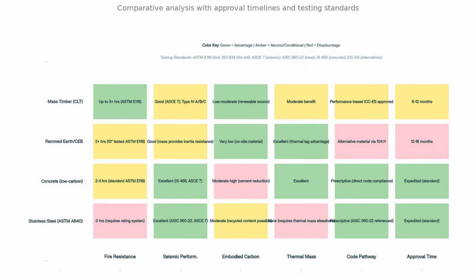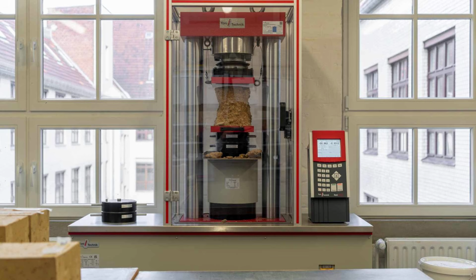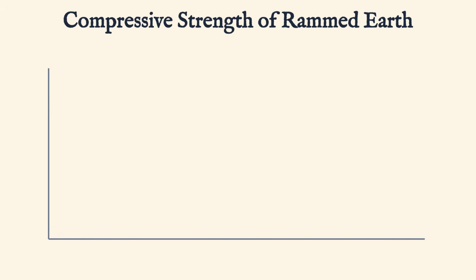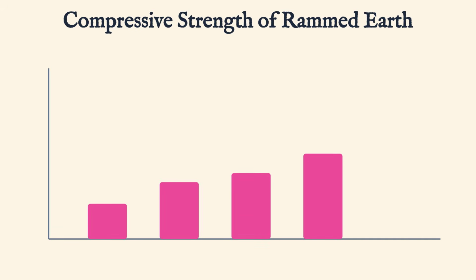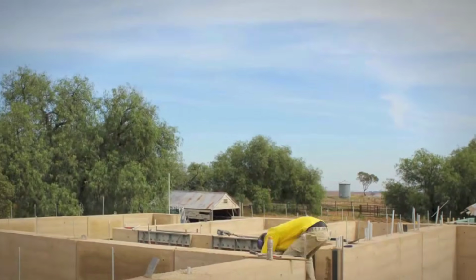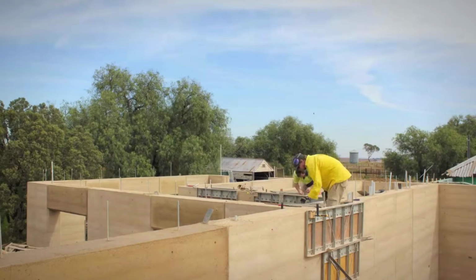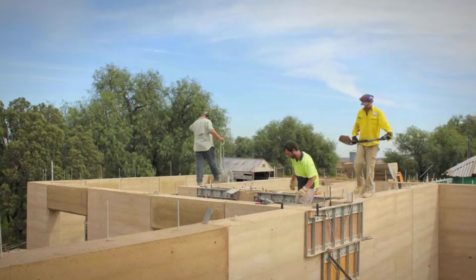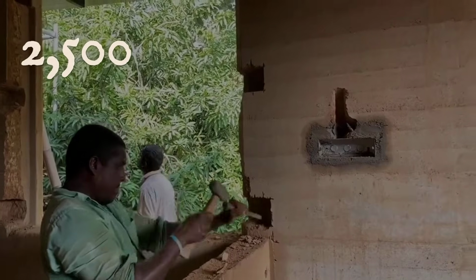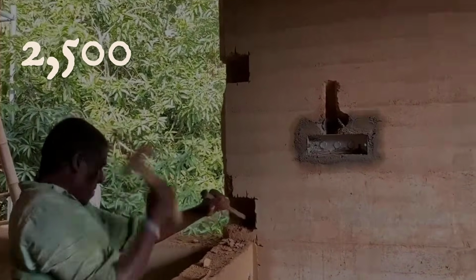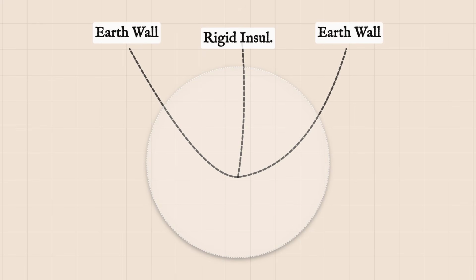Building codes in Australia, New Zealand, and parts of Europe set the minimum compressive strength for load-bearing rammed earth at 2 megapascals, about 300 pounds per square inch, but modern techniques routinely double or triple that figure. In the Skagit Valley project, for example, architects specified 24-inch thick earth walls with a compressive strength exceeding 2,500 pounds per square inch, sandwiching an 8-inch layer of rigid insulation for even greater energy performance.